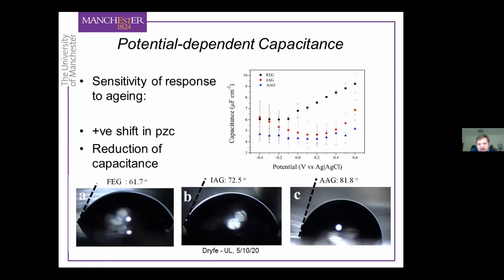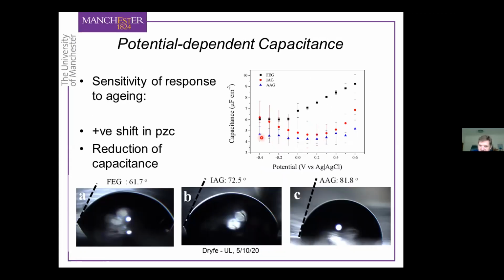So you can see these effects if we look at the potential dependent capacitance. The black symbols are the capacitance as a function of potential for the freshly exfoliated graphite. The red symbols are the capacitance as a function of potential when we let the graphite age in a glove box, and the blue symbols are the capacitance response when we let the graphite age in the open laboratory. So you can see two things. You can see that the capacitance is reduced by the adsorption of this extra layer on the surface, and you can also see that the minimum in the capacitance has moved to more positive potentials, although it's harder to see in the atmospheric age case because the capacitance potential response is shallower.